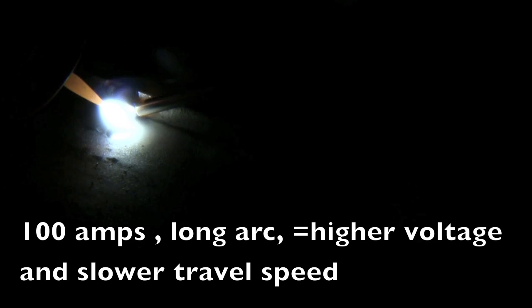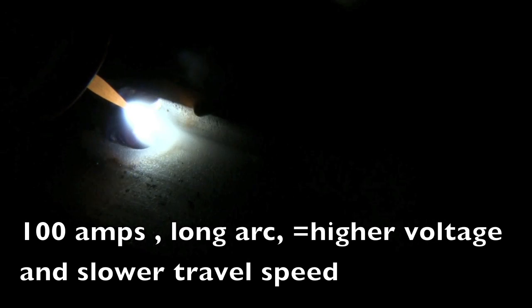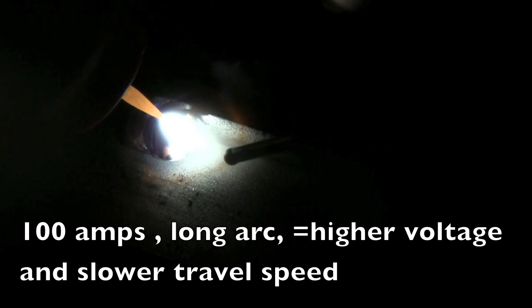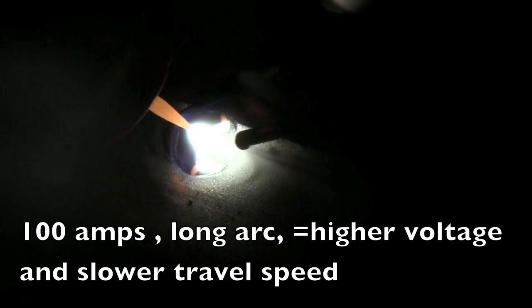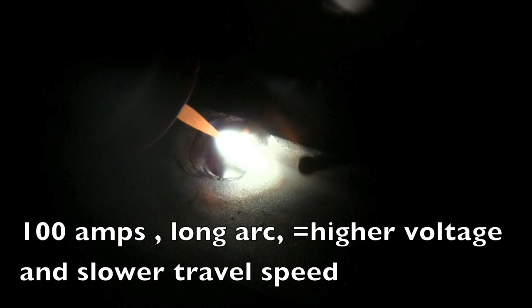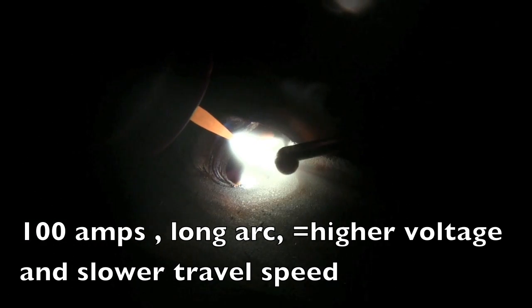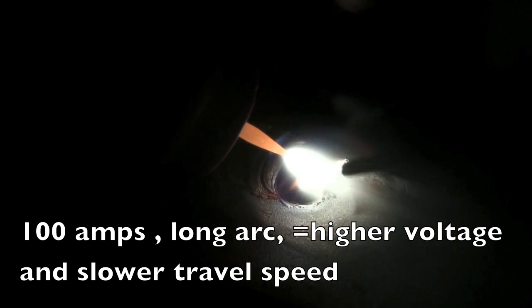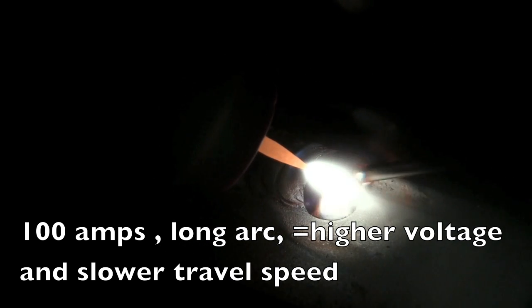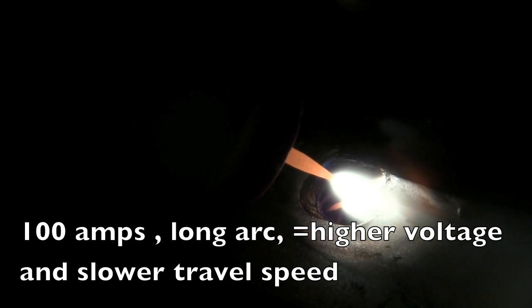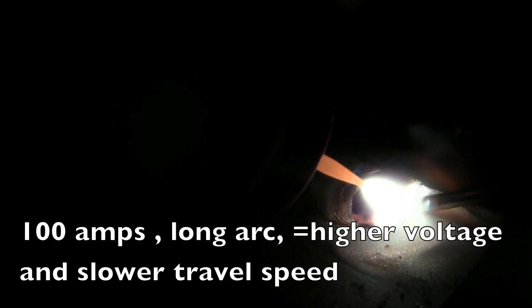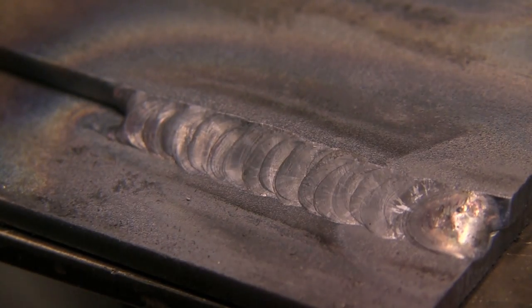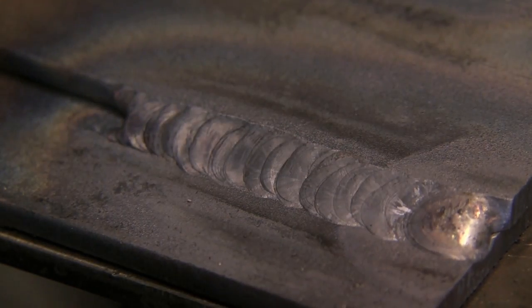A good example of this is holding too long an arc. When you hold too long an arc in TIG welding, you increase the voltage. You don't pinpoint the heat. It takes a little bit longer to melt everything. Things don't go together like they should because you're fanning the heat out there. You're not directing the heat, so you're slowing travel speed down, and you're increasing voltage. The rod is balling up and blobbing in there, and you get an oxidized looking surface because the metal is still terrifically hot while the argon leaves it, and just not what you're looking for from a TIG weld.